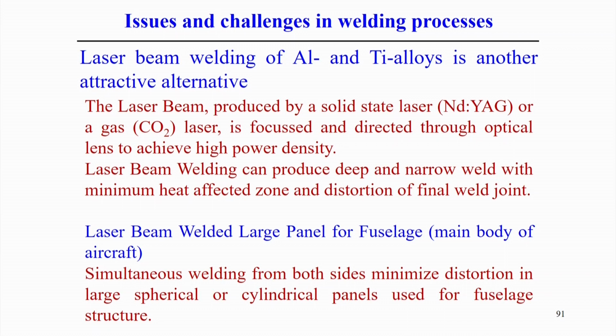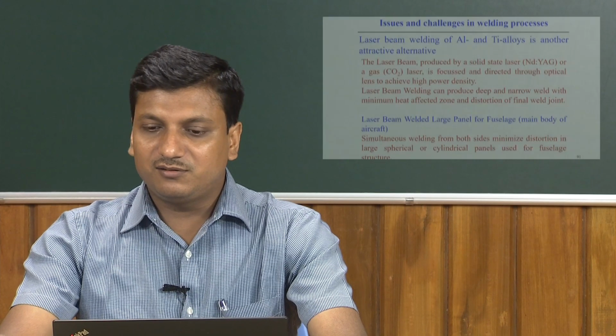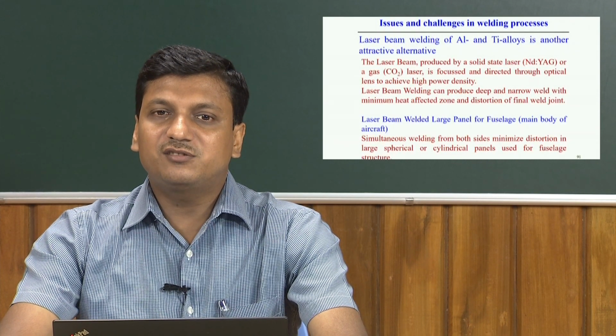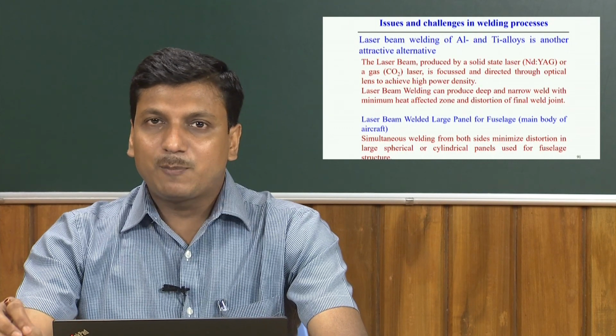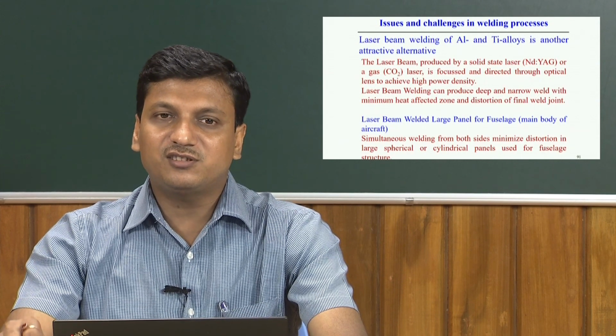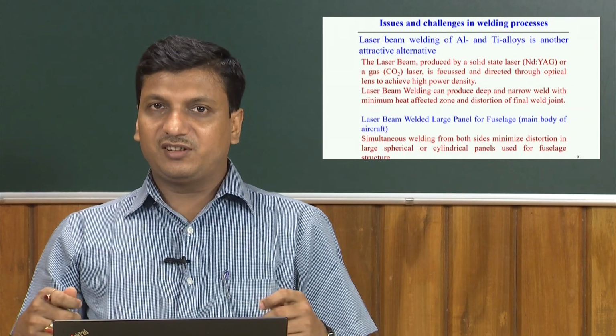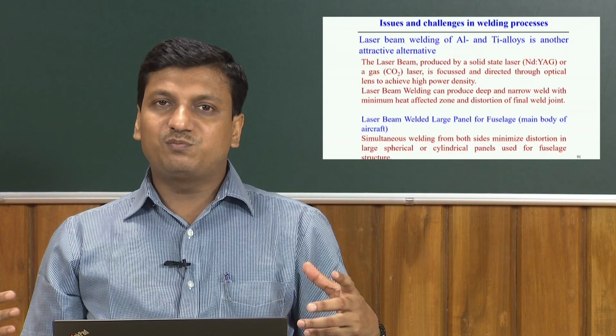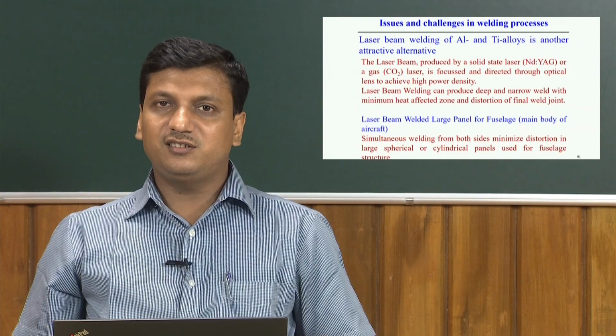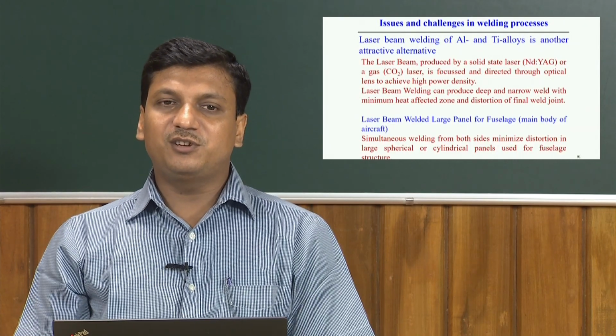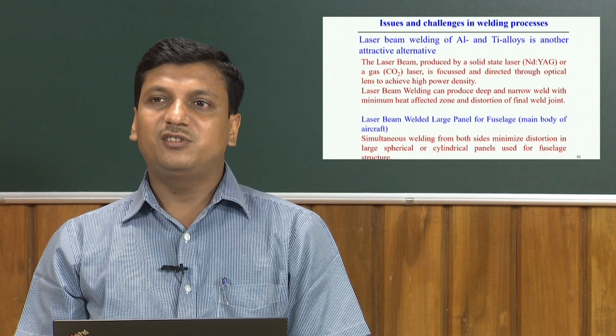For example, in welding of titanium alloy using the laser welding process, extra shielding gas sometimes may not be required, as the shielding provided during laser welding is sometimes advantageous, or otherwise the welding can be done in a separate vacuum chamber. But mainly for the large panel fuselage, that is the main body of the aircraft, we generally apply the laser beam welding process, because of simultaneous welding from both sides. The path of the welding is very important. If you choose the proper path, with simultaneous welding from both sides, that minimizes the distortion in very large, spherical or cylindrical panels used for the main part of the aircraft body.